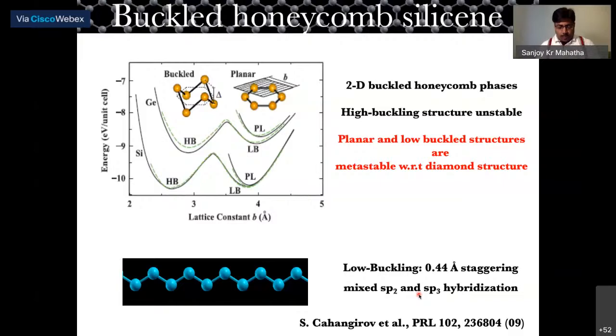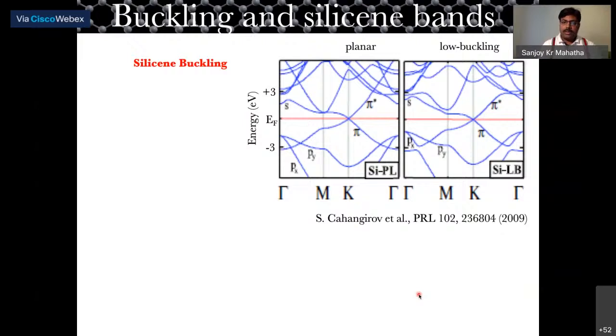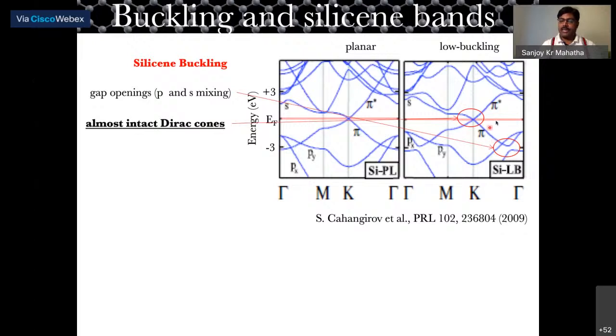Okay, and what should we expect in the electronic structure? This is the silicene band structure with planar silicene, where all the silicon atoms are on the same plane, and this is low buckled silicene. That means one silicon atom is at a different height with respect to another, 0.44 angstrom higher than the other one. If you compare their electronic band structures, you can see that the band structure is nearly the same. There is no big difference, except there is a gap opening here. This is because of S and P mixing, because of some sp3 hybridized bands. But most importantly, the Dirac cone is intact. So even if we get a low buckled silicene structure, we should expect to see some kind of Dirac cone, because there is no change in the Dirac cone.